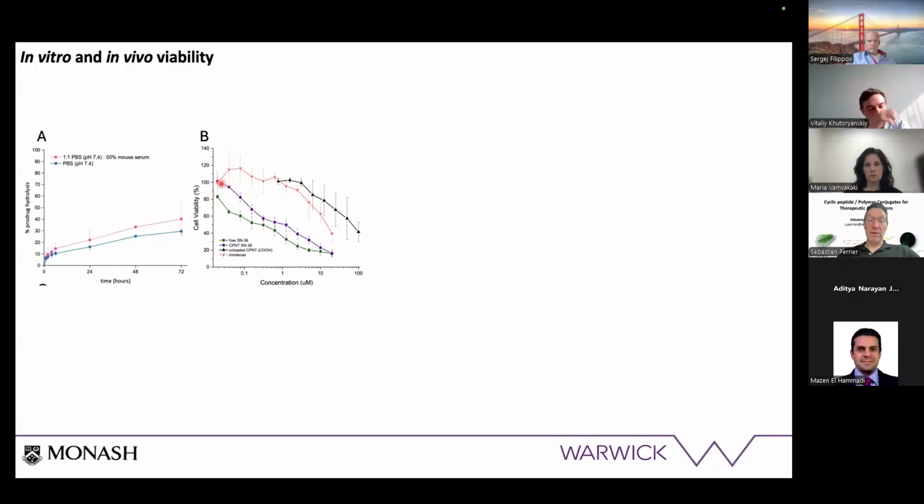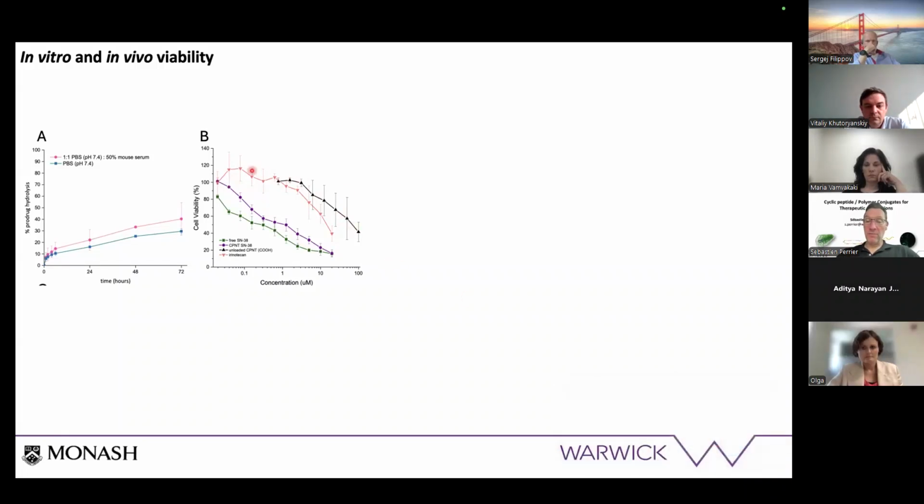Our polymer nanotubes are almost as efficient as SN38. Attaching SN38 to our nanotube doesn't change much of its activity, and it makes it much more efficient than irinotecan. What you have here in black is basically the fact that our nanotubes are not active, so you find that they're not toxic. The toxicity we observe here really comes from SN38 rather than the nanotubes. You can go to very high concentrations of nanotube before you start seeing some toxicity. So that got us really excited.